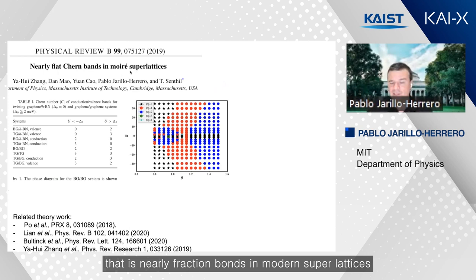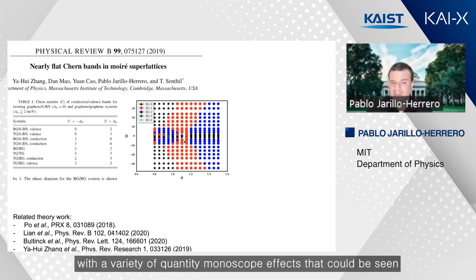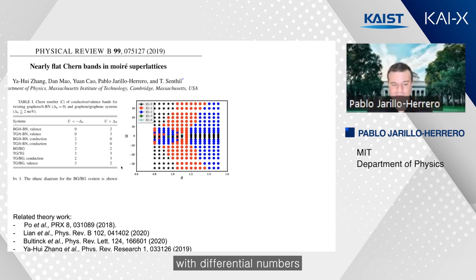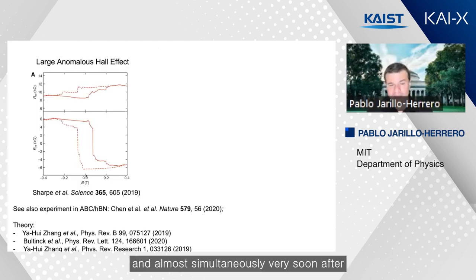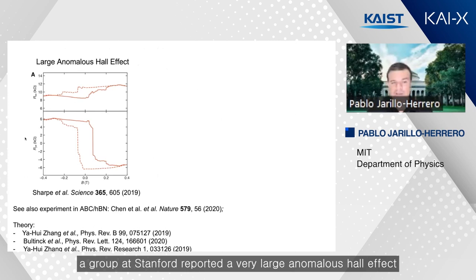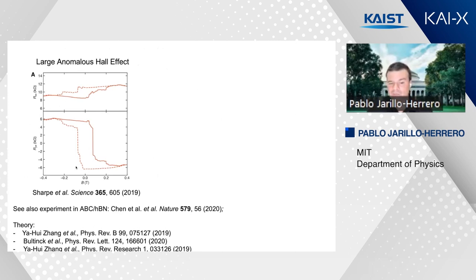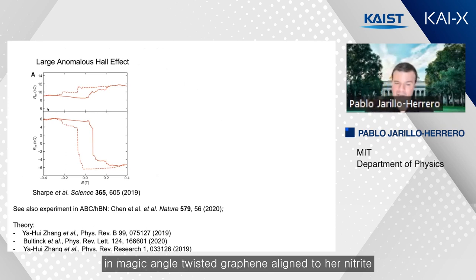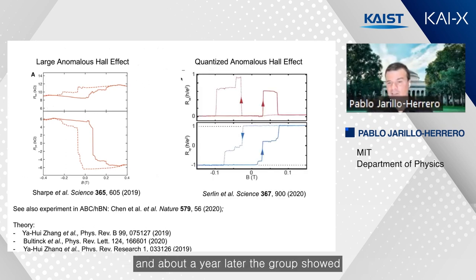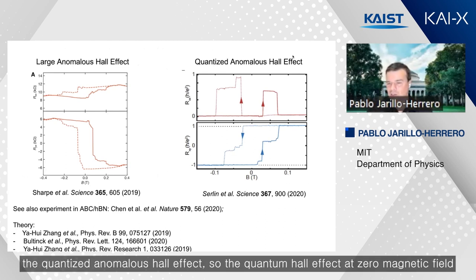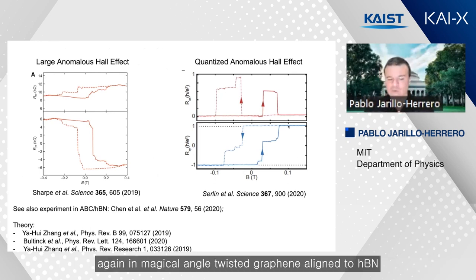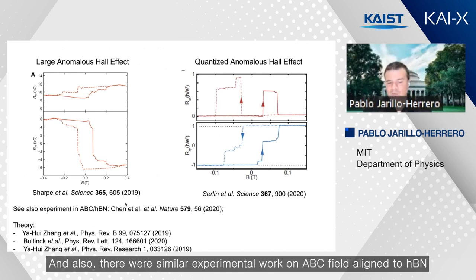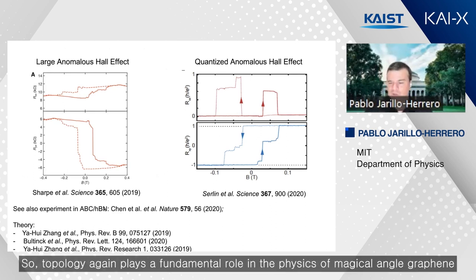So in fact, back in 2019, we predicted together with my theory colleagues at MIT that there would be these nearly flat Chern bands in moiré superlattices with a variety of quantized anomalous Hall effects that could be seen with different Chern numbers. And there was related theory work. And almost simultaneously, very soon after, the group of David Goldhaber-Gordon at Stanford reported a very large anomalous Hall effect in magic angle twisted bilayer graphene aligned to hexagonal boron nitride. And about a year later, the group of Andrea Young showed the quantized anomalous Hall effect, so the quantum Hall effect at zero magnetic field, again in magic angle twisted bilayer graphene aligned to hBN. And also there was similar experimental work on ABC trilayer graphene aligned to hBN. So topology again plays a fundamental role in the physics of magic angle graphene.